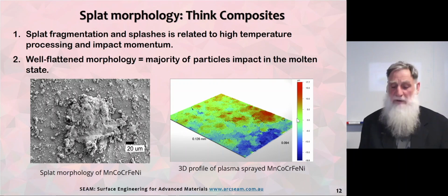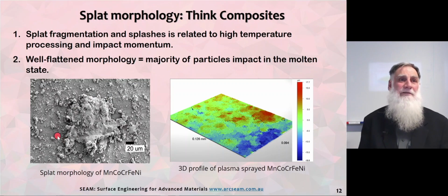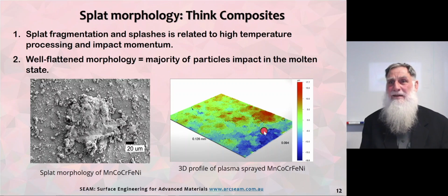So more sophisticated work on splat morphology looks at individual splats. Here is a real splat, which is actually a high entropy alloy in this case, of manganese, cobalt, chromium, iron and nickel. And we have a splat which appears to be partially melted. And we have the splatter marks of impact and fragmentation against this small surface. That is related to high temperature processing and the impact momentum. And you can also reveal these splat morphologies by carrying out 3D profiles under optical sensing devices. Here you see a splat which is raised above other splats underneath, and you can see splats being formed and being revealed across the surface which is being sprayed.